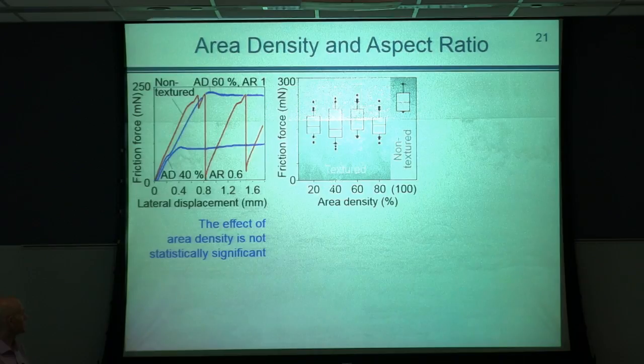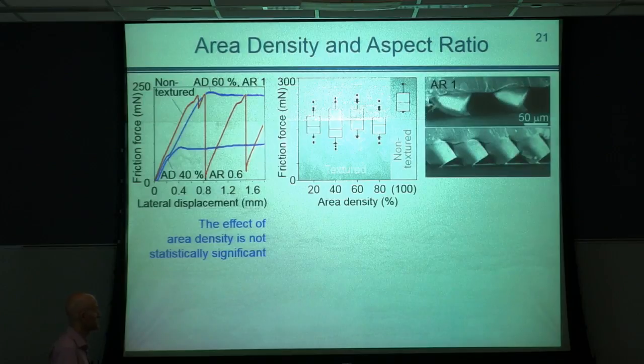So what you see here is friction force represented as a function of area density, the area covered by these hexagons over the total apparent area. And we can see that actually area density does not affect friction force. And these are two images from SEM that suggest some explanation.